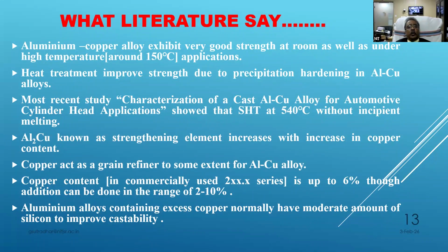So literature says that aluminum copper alloy gives very good strength at room as well as under high temperature conditions, around 150. It is already mentioned. Now heat treatment again improves its strength, its wear characteristics, and also the characterization of cast aluminum copper alloy. We have seen that finally, the solution heat treatment we have done. I will show the graph. We will show the heat treatment curve, and after that we will find that Al2Cu, which is basically the theta phase of the alloy, staying in the grain boundary, is basically strengthening, and it increases with the copper content. If you increase the copper content, then Al2Cu comes in the grain boundary and increases. As it increases, the total matrix gets more strengthened.